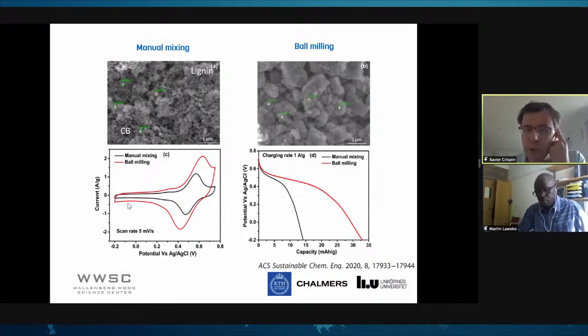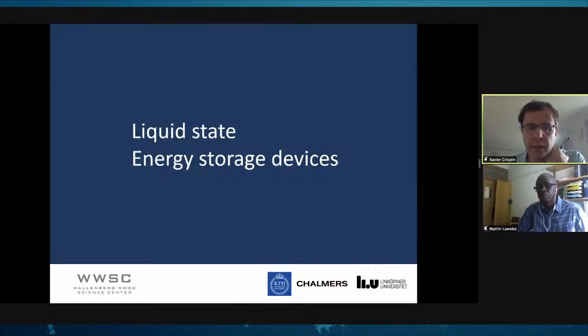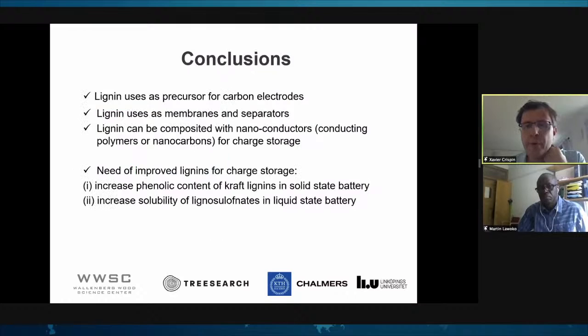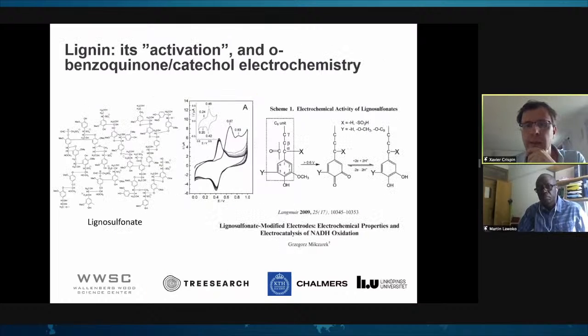Of course, you can probably over-oxidize the lignin and start to attack it. That is for sure. And what we have observed is that, depending on the preparation of lignin, the first peak that you typically observe is a reaction where you basically remove the methoxy group, so to get this kind of oxidation, which is actually very important because it enables the lignin to be prepared for storing more charge. This is a reaction that we have not fully understood.